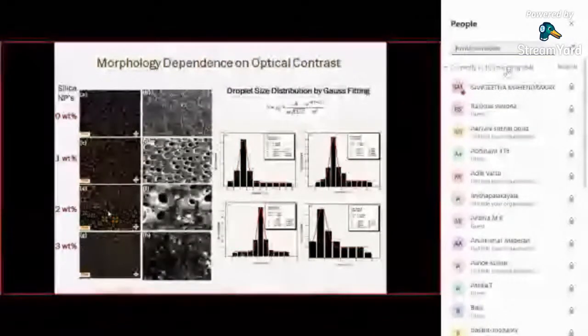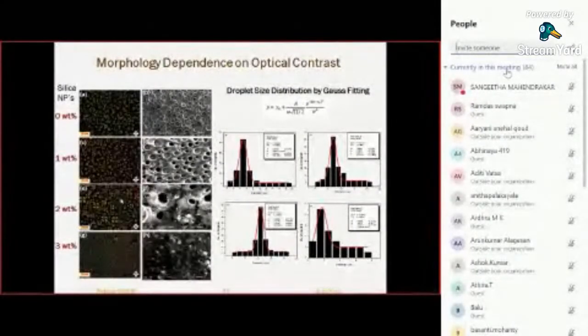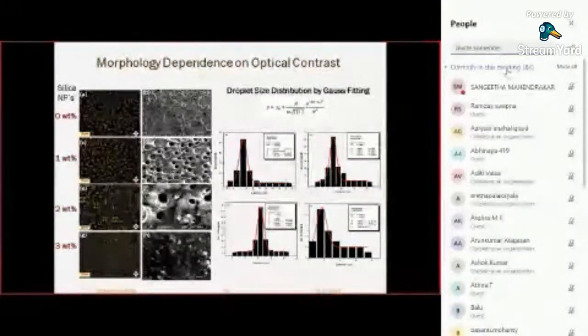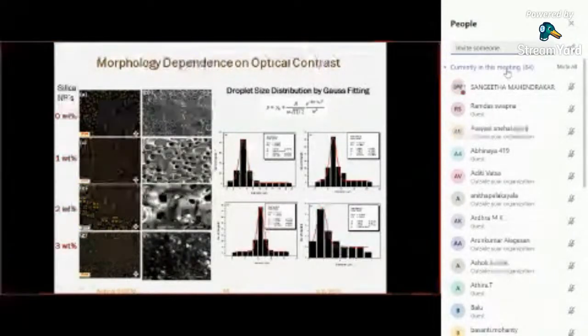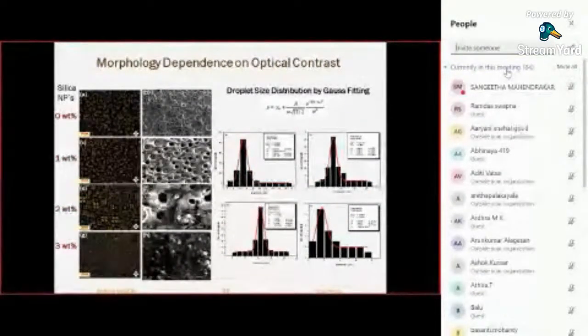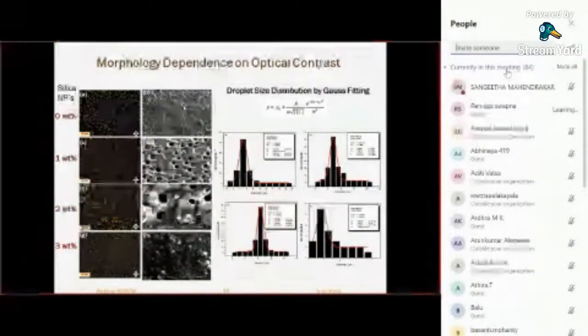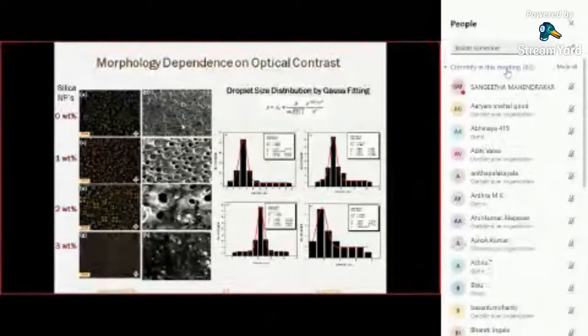And when we remove the liquid crystal from this cavity, only the polymer structure is left, and this structure was investigated through scanning electron microscopy. These are the micrographs taken from the scanning electron microscopy to investigate these droplets and this polymer matrix structure. See, from this matrix to this matrix, the polymer matrix surface can also be modified with the help of nanotechnology.